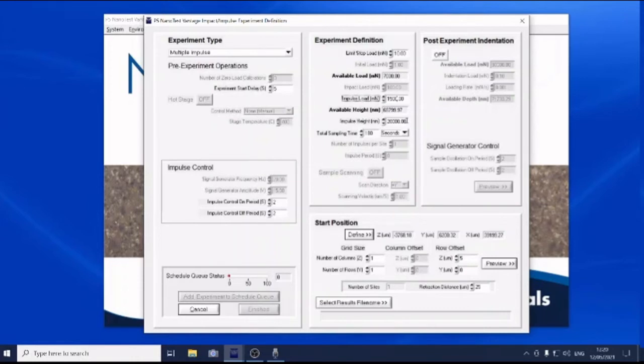And the final thing of significance, perhaps, is the acceleration distance. We normally set that with micro-impact testing to 20 microns. You can set it to longer or shorter, depending on what you want to achieve, but typically we use 20 microns. So basically, the probe will be accelerated over a 20 micron distance with 1.5 newtons of accelerating force. It hits the sample surface, will stay there for 2 seconds, and will be withdrawn. That process will be repeated 45 times. That's a 4-second total cycle time and 180 seconds total sampling time, so actually 45 impact events.